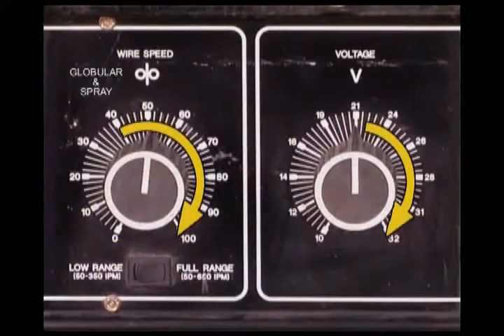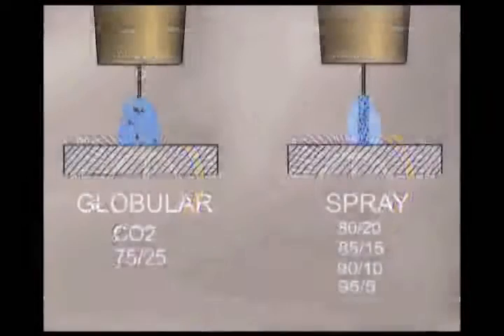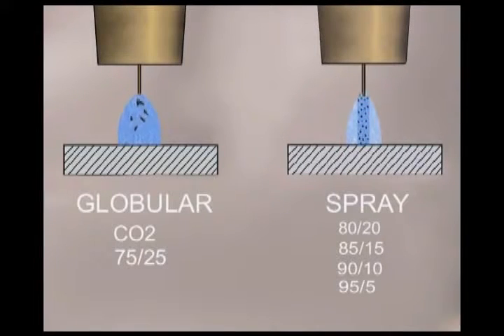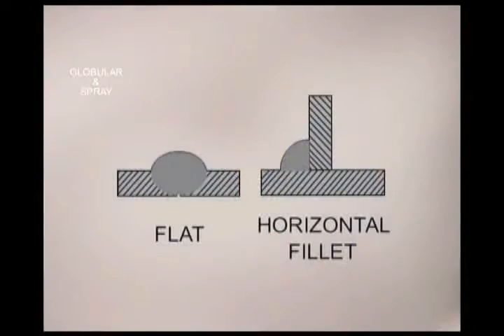We've been demonstrating all position welding and weld joints with the low voltage range short circuit metal transfer. For faster deposit rates or better penetration, using the same filler wire, you can turn up the voltage and wire speed. Over 22 volts, you'll have an open arc and globular transfer with carbon dioxide or 75-25, or spray transfer with an argon-rich gas. From the welder's point of view, these are similar, and while it is high-speed welding, it's also very simple. Because of the amount of heat in filler metal, these are generally used only in the flat position or for a horizontal fillet, which is basically flat.